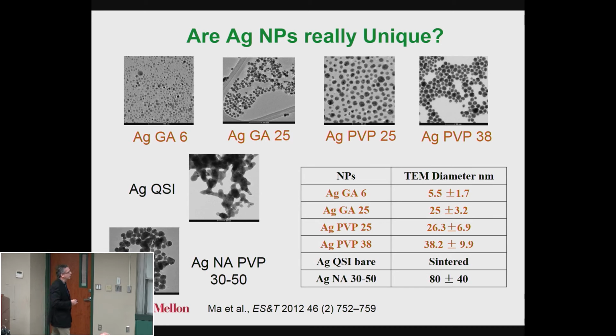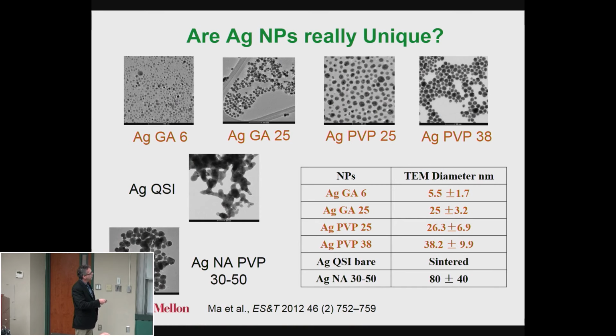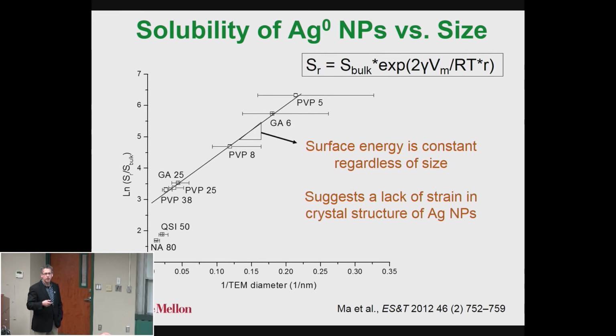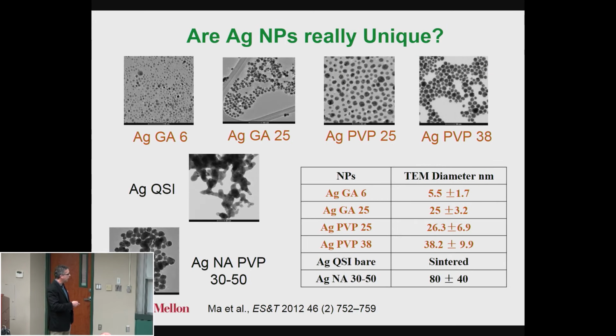Okay, so we just set out to say, all right, are they really unique? Are they special from a molecular point of view? So we made a bunch of nanoparticles, and they had different coatings, PVP or gum arabic, but we had 6 nanometers all the way up to some sort of bulk size materials, okay? And the first thing we did was we just measured their dissolution rates, right? So we have all these particles, and you would think, all right, different sizes, you get different dissolution rates, but if I surface area normalize, I should get the same value.